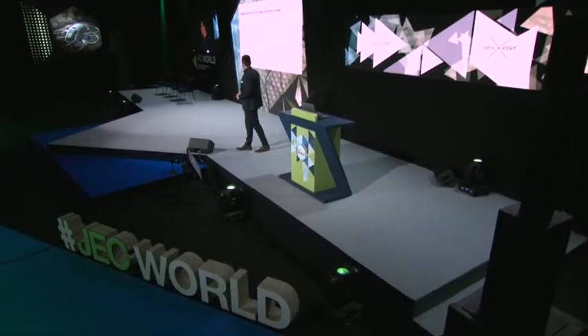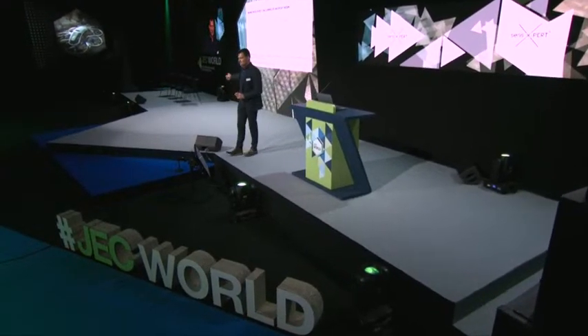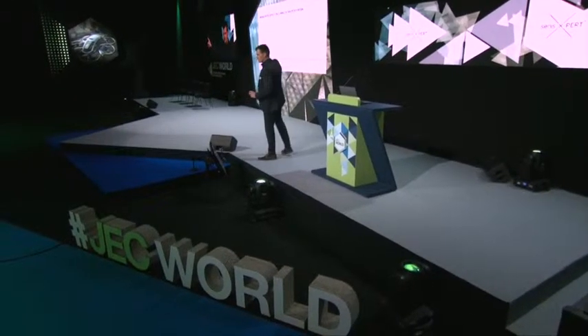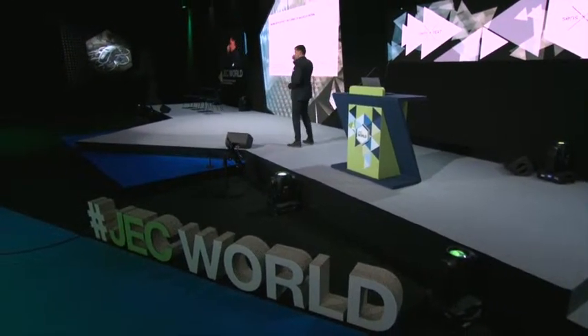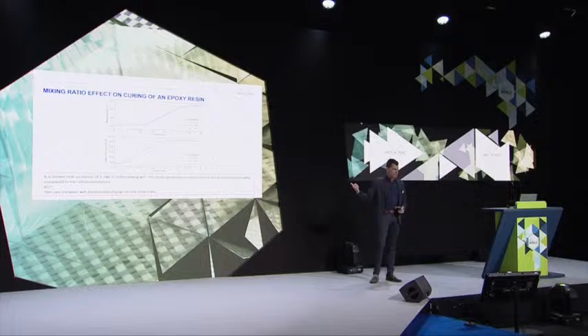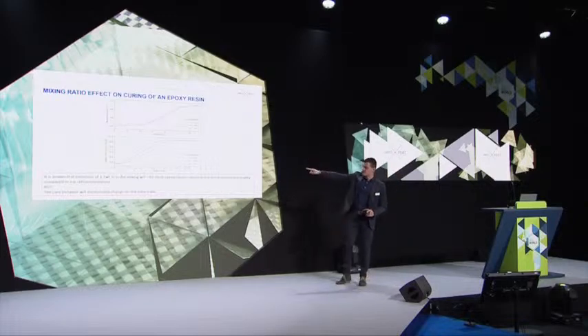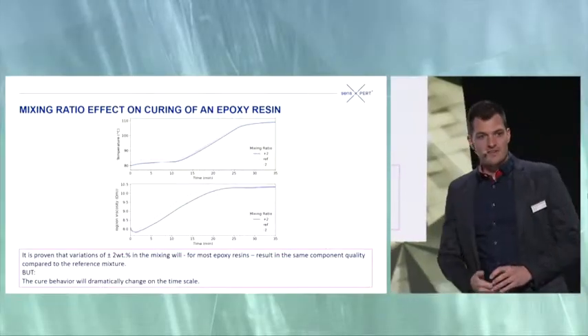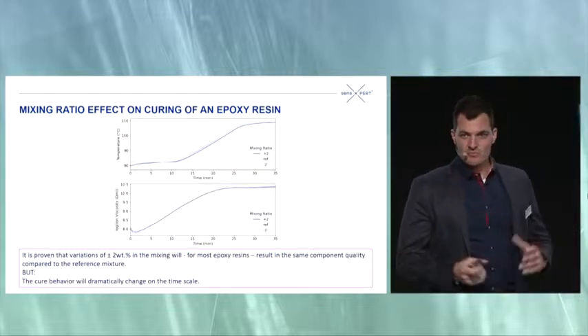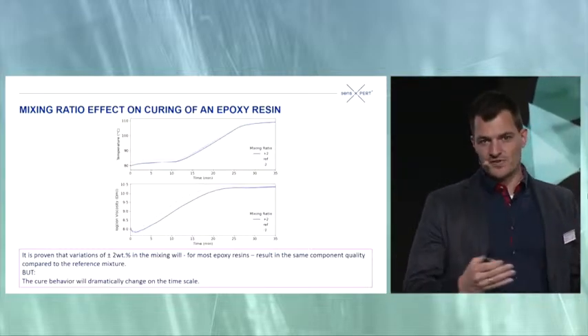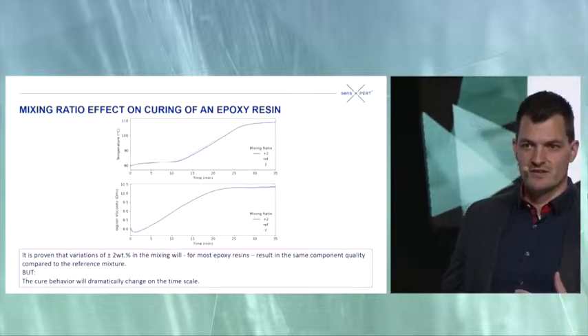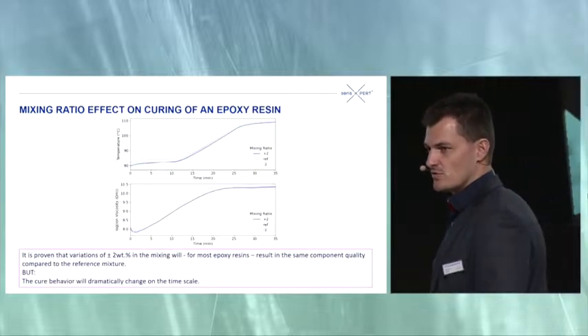But during production, we can see that the cure behavior is totally different. And in this case, and that's quite exciting to see, usually I would say if I have more hardener content, the system should cure faster. But it's not. It's somehow blocked. You can see that the reference mixture is the fastest one, and the two with minus 2% and plus 2% of hardener content are slower in curing.